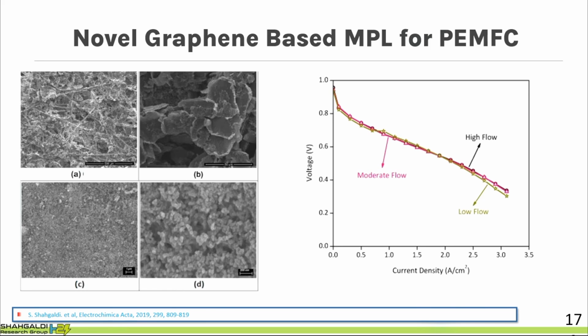So this is also one of the interesting results that we published back in 2019. We applied graphene and carbon-based material for the MPL. We somehow optimized the amount of ionomer, type of ionomer, and how to build the catalyst layer all together, okay? And then we ended up with an MEA that is not sensitive to the flow. For the people that are in the field, they understand that. What does it mean? It means that you produce an MEA that, if you have high flow, low flow, or moderate flow, you will end up with the same performance. It means that you will have a perfect porosity in place. When you run it, you have enough reactant to run your fuel cell. So the conclusion is that if you know what operational condition you want to run your stack, then it's easy to build a proper MEA for your purpose.